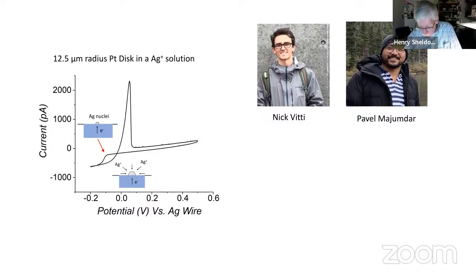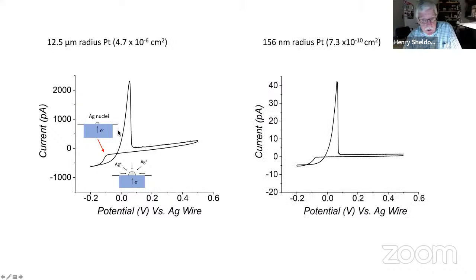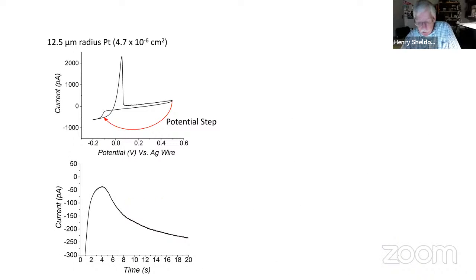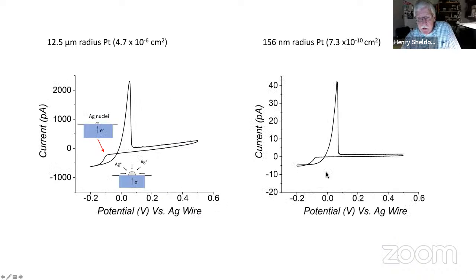This is a really old experiment that a lot of you probably have done. And if you do this with a tiny electrode, so this is a platinum nanodisk with a radius of 156 nanometers, you get the same response. In fact, you really can't tell the difference between these unless you look at the current scale. All right, you scan out, you nucleate a particle right here, and you grow it by diffusion limited growth, and you can strip the particle off, and this is reproducible.